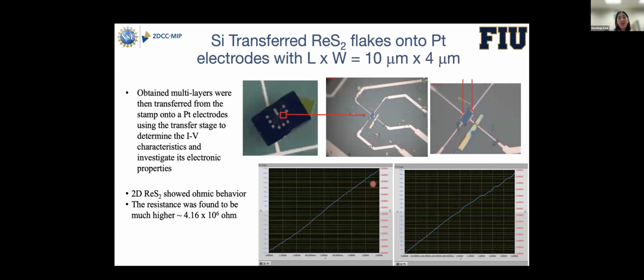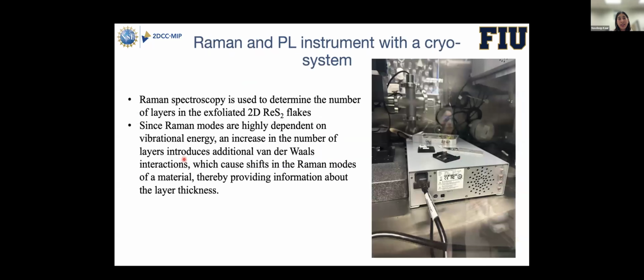So we wanted to transfer that 10 by 4 micron flake, which was now a multi-layer, from the silicon substrate to platinum electrodes, which we have used. This is the image of those platinum electrodes. Using the same transfer stage setup, we picked the flake from the silicon substrate with the PDMS dome, and then put it onto these platinum electrodes. Then we did the electrical measurements of the material, and it showed an ohmic behavior with a pretty high resistance, nearly 4 × 10^6 ohms.